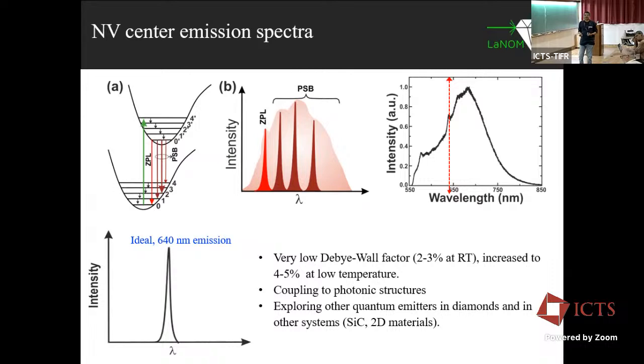And if you measure these emission spectra in the laboratory, this is some measurement from our lab, intensity as a function of wavelength, you can see a very broad emission spectrum. And the zero phonon line at 637, which is a pure electronic transition, is very feeble and weak. This is interesting for many applications in quantum technologies, because the zero phonon line is very coherent, and all these phonon sidebands induce decoherence in the system. So people try to avoid it somehow.